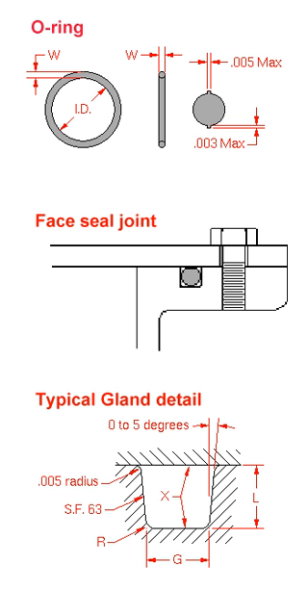Vacuum applications: In vacuum applications, the permeability of the material makes point contacts quite useless. Instead, higher mounting forces are used and the ring fills the whole groove. Round backup rings are used to save the ring from excessive deformation. High vacuum systems below 10⁻⁹ torr use copper or nickel O-rings. Vacuum systems that have to be immersed in liquid nitrogen use indium O-rings, because rubber becomes hard and brittle at low temperatures.